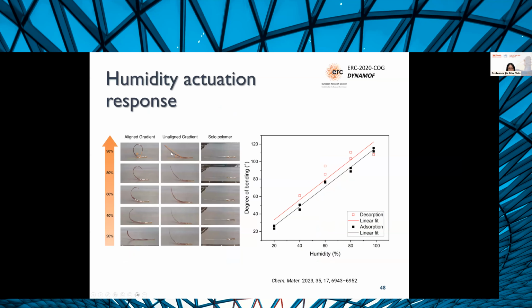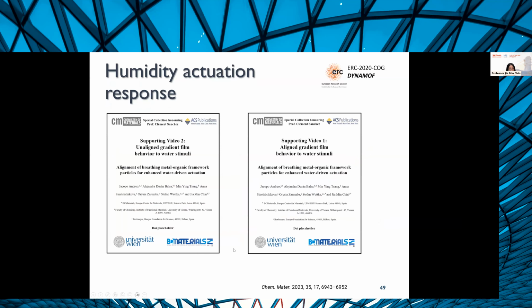Now, if you look at the aligned versus the unaligned film, you actually see that there's a huge difference in the performance. And in this case, we use a lot less MOFs than what is typically used in previous examples of MOF actuators. Here we used about, I think, 18 to 20%, whereas in previous examples, typically they need 50% of the MOF. And you see that alignment makes a big difference in the response.